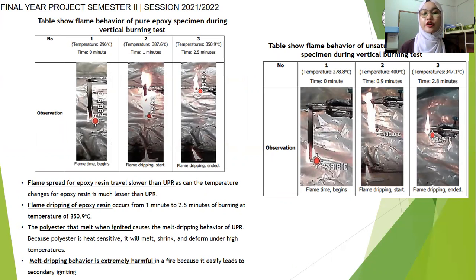The flame spread for epoxy resin travels slower than UPR. However, both show a melt dripping behavior. As for UPR, the reason for its melt dripping behavior is because of polyester. The polyester in the UPR is heat sensitive. That is, when it experiences heat, it will melt, shrink, and deform. Melt dripping behavior is harmful in a fire as it will lead to secondary ignition.